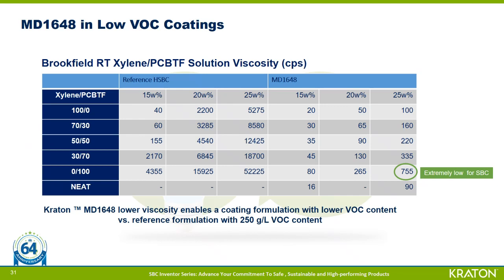So with sealants and coatings, we have a comparison of a reference HSBC and MD1648 as designated in the top blue row. So here we have xylene and PCBTF, which is a VOC exempt solvent, and this is located in the far left column. The center dark and light gray boxes illustrate the solution viscosities in the system for a given polymer loading level and for the VOC solvent ratio.